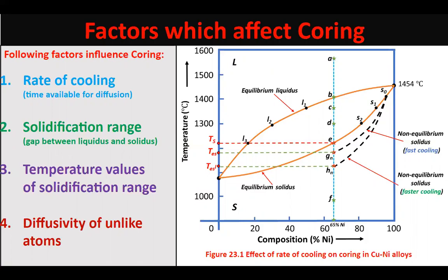Because of this faster rate of solidification as compared to the rate of diffusion, in the final microstructure obtained in the alloy, a cored type of structure has formed. Cored in the sense that there would be regions in the center of the grain which would be rich in one type of constituent element, generally the high melting point element.